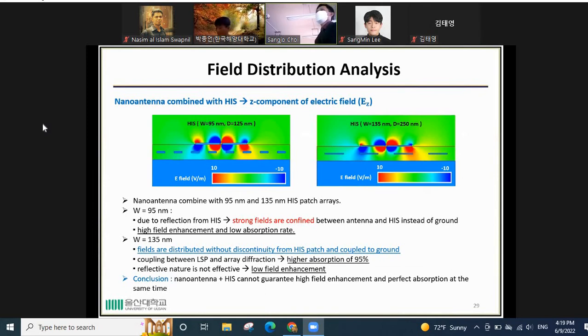To understand the phenomena, we also analyze the electric field distribution along the Z-axis between two different patch sizes of the HIS, 95 nanometer and 135 nanometer. From the left figure, we can see that because of the reflection from the HIS, strong field is confined at the antenna center between HIS patches and the antenna. This structure shows high field enhancement and low absorption rate.